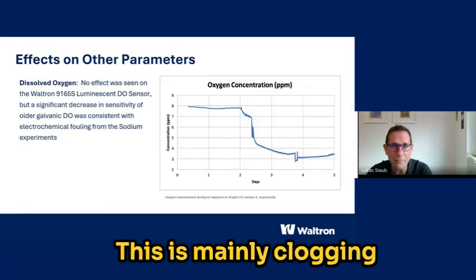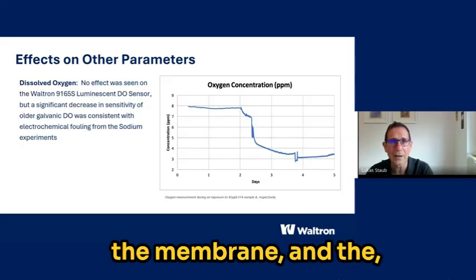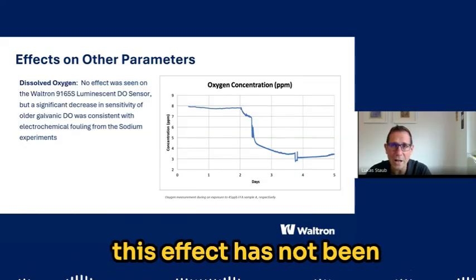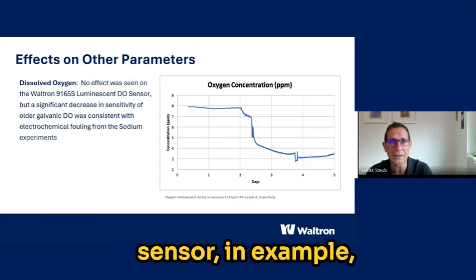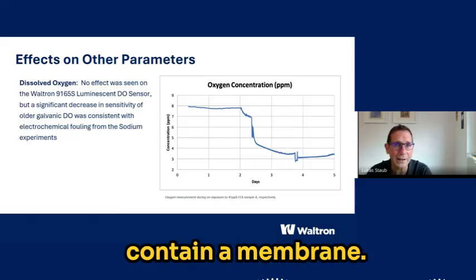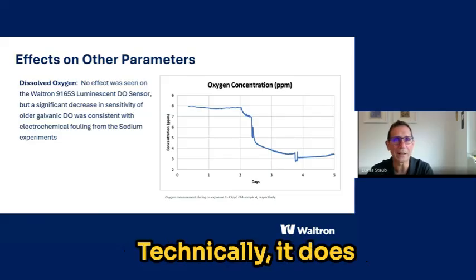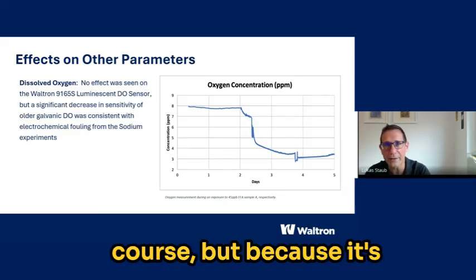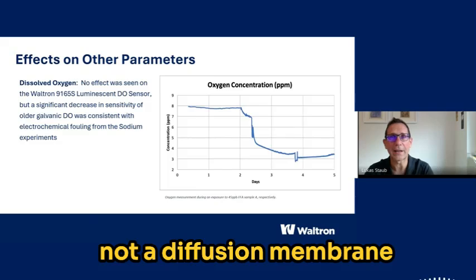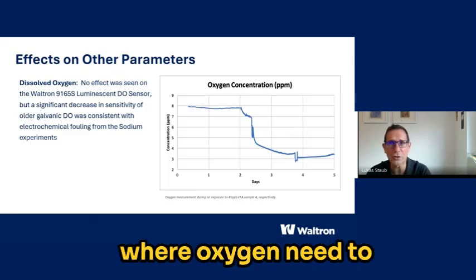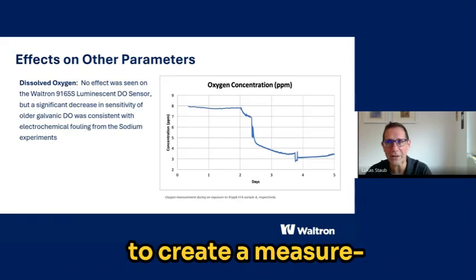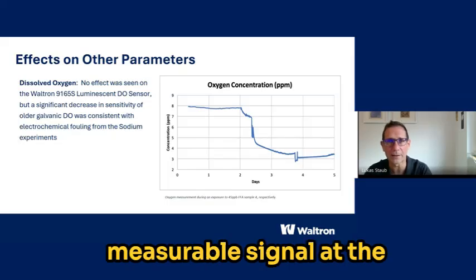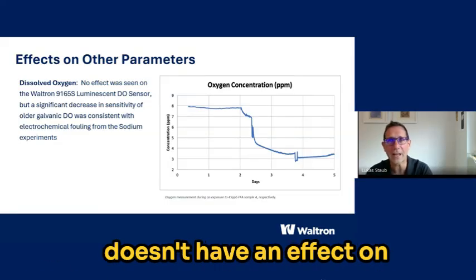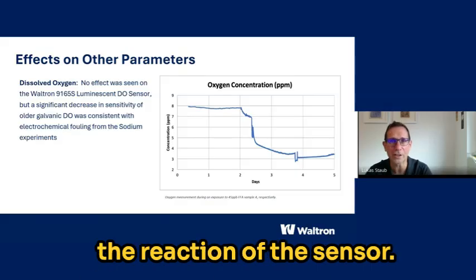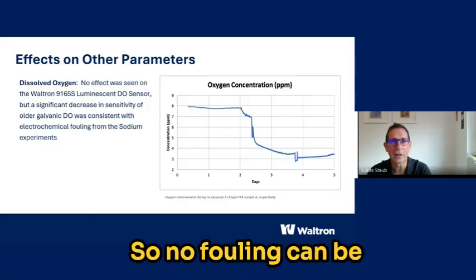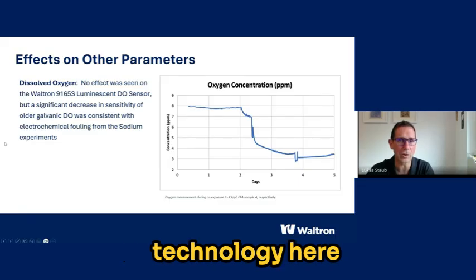This is mainly clogging the membrane, and this effect has not been seen on a luminescent sensor, for example, because it doesn't contain a membrane. Technically, it does contain a membrane, of course, but because it's not a diffusion membrane where oxygen needs to pass through in order to create a measurable signal at the measuring electrode, it doesn't have an effect on the reaction of the sensor. So no fouling can be seen with luminescence technology here.